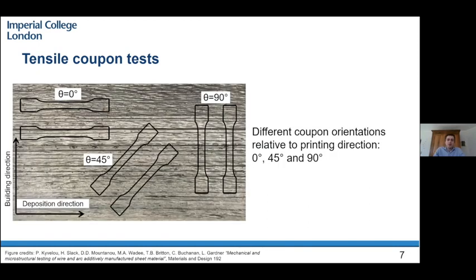To get an idea how the VAM material behaves in different orientations, we cut tensile coupons from different orientations of the same sheet metal, printed using VAM. A 0-degree coupon means that the deposition direction is parallel to the tensile direction of our tensile coupons, and then relatively for the 45 and 90-degree directions.